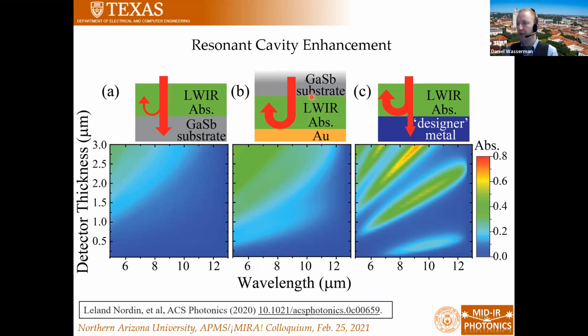But of course, to do that, you'd have to coat one side and you'd have to come in from the back side. We can, of course, grow our long wave IR absorber right on top of one of our designer metals. And what you actually see is that certainly at these long wavelengths and very thin detectors, you get a significant enhancement compared to the other two. But even at moderate thicknesses, you can get a rather significant enhancement. And it ends up being a significant enhancement in integrated absorption as well.